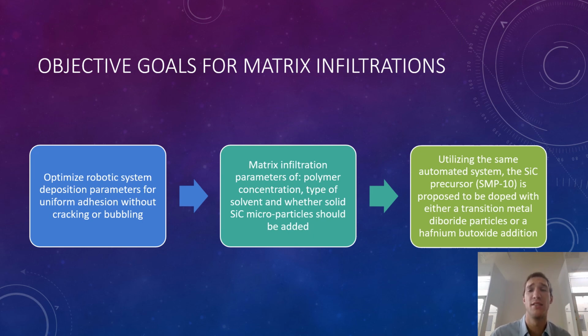And then using the same automated system, the silicon carbide precursor is proposed to be doped with either diboride particles or, more notably, a hafnium butoxide addition to increase the thermal resistance of these CMCs, and thus increase the operating temperature at which they can survive and fully operate.